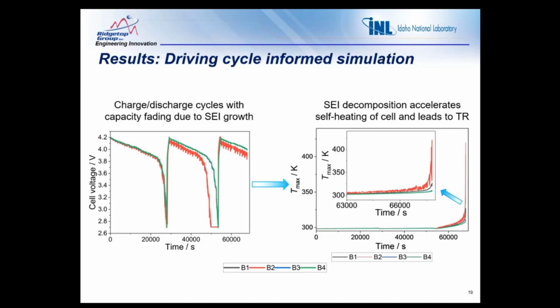But as the SEI decomposition, that's mostly prominent in our faulty battery B2, accelerates self-heating, it exhibits a sharp rise in temperature. The red curve for B2 shows an exponential temperature increase, which is characteristic of thermal runaway. This behavior aligns with the Arrhenius equation, which explains the exponential dependency of reaction rates on temperature.